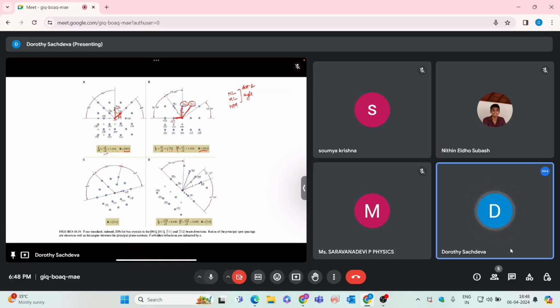Also you should remember about the reflection, forbidden and allowed reflection, just as we discussed in the XRD. For the FCC your HKL conditions, and for BCC your HKL conditions are different for allowed and forbidden. So in this case, 100 is not allowed. So this spot won't be present. So if you are seeing this 200 spot, then there should not be any spot halfway between the direct spot and 200, because in this case 100 doesn't exist. So you should remember these rules, and you can look at the standard diffraction patterns in these cases.